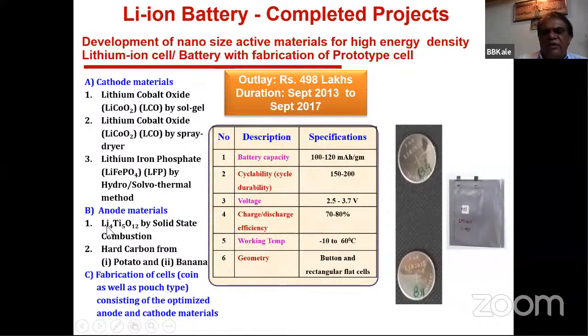The advantage of lithium titanium oxide is it's very stable, and it doesn't react easily with the electrolyte. Carbon sometimes gets deactivated due to the electrolyte, and hence in hard carbon the major problem is capacity fading. Initially we have 300 milliamp-hours per gram, but after a few cycles we may have some 100, 120. So again, this is a big problem with the carbonaceous material.